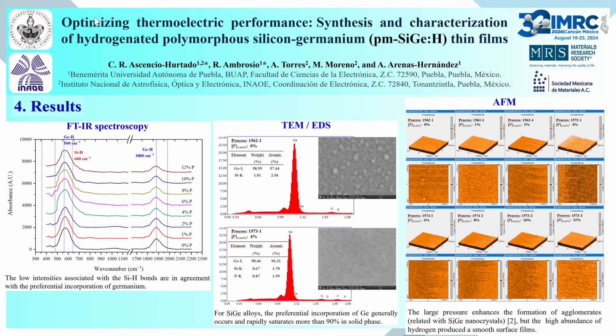Let us remind that the high conductivity obtained for 0% was produced by the deposition conditions and the nanocrystal formation. It is very well known that the nanocrystals help to reduce the weak silicon-silicon bonds, but the addition of phosphorus seems also to behave as a catalyst for this action. We may say that the phosphorus content increases the germanium-hydrogen and silicon-hydrogen bonds in their bending mode and reduces the density of the germanium-hydrogen bonds in stretching mode.